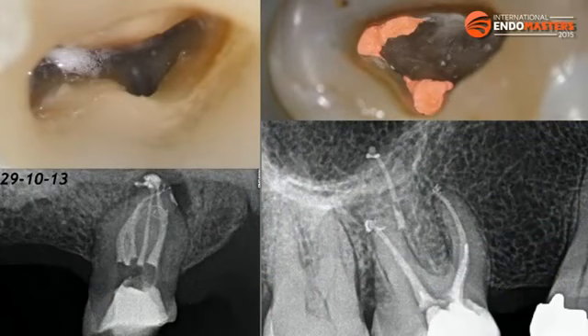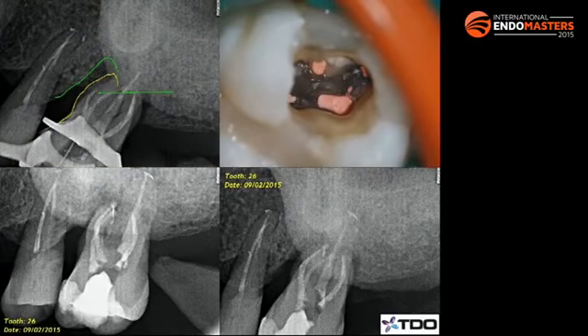These two cases are a clear example of the benefits of using a technique that makes the most out of the properties of current materials, such as the hydraulic flow of the cement and the adaptation of the semi-solid material, in this case gutta-percha, to seal the anatomy of these complex and irregular root canal systems. On this molar, for example, if we focus on the images on the X-ray, we will see that the canals do not seem to be very oval, but in the clinical picture on the top right, we can see that we managed to fill the entire shape of the canal with the gutta-percha without having to rely too much on the cement.